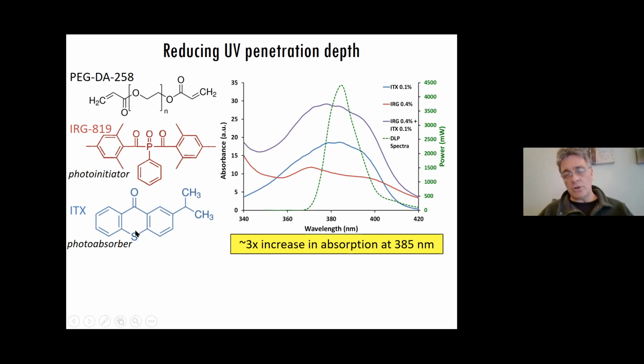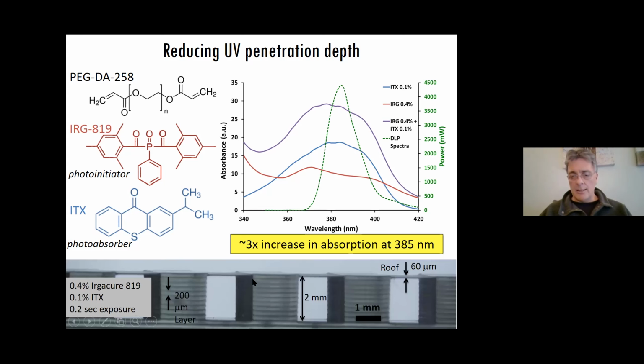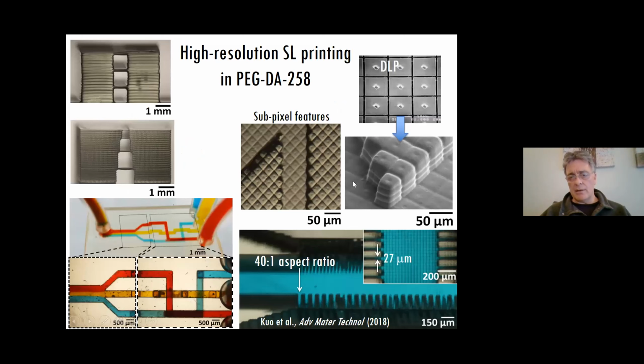And then we worked on adding ITX, which is essentially a photo absorber. It helps in absorbing more, essentially increasing the absorption at the lamp's wavelength. And so that also added an element of resolution in Z especially. That was very important for creating the roofs in microfluidics, and that helped us to create high resolution prints in